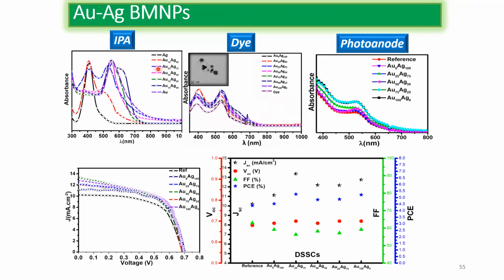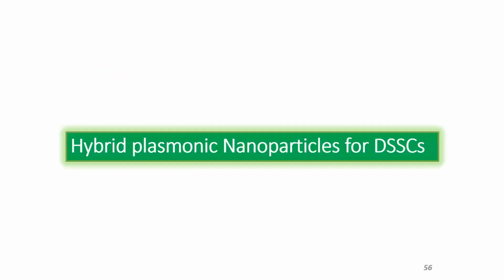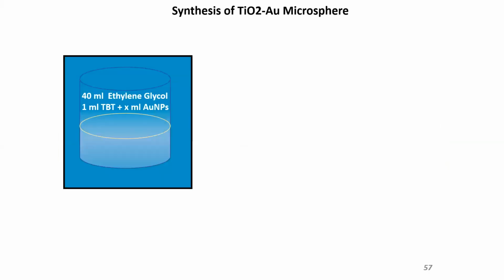It does not work with all compositions. It can work with particular compositions only. I found that when I used gold 25 and silver 75, it forms a really better alloy. And I have utilized this material for solar cell applications. Now, I made a good plasmonic nanomaterial, but where will I put it? The better host. Up to now I just used the normal TiO2 nanoparticle. Now I thought I should make a better host that absorbs even more light by itself, and the plasmonic can just add its effects.